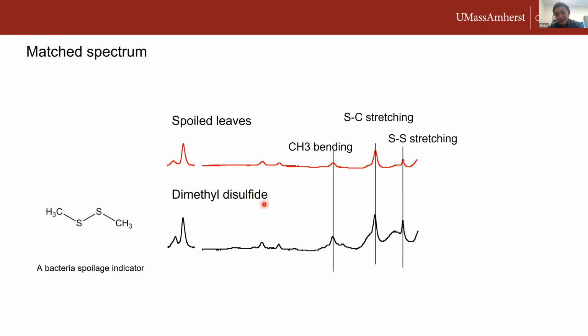As we can see on the top of the spectra, this is the spoiled leaf spectrum collected from the SERS fiber. And this is the reference of dimethyl disulfide. Then we can see that we have three characteristic peaks that match pretty perfectly. They are the CH3 bending, carbon to sulfur stretching, and sulfur to sulfur stretching bonds.